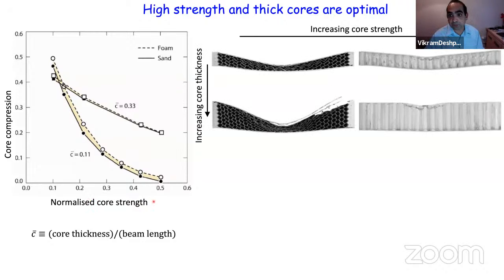strong core helping. Okay, so to give it visually, to explain what has really happened, is this story here: as you increase the core strength, you hardly compress the core, as you can see. This is a weak core, it's compressed a lot and it's lost all its bending strength, while this core strength remains very large. If the core strength is large, you retain this separation of face sheets and you basically retain the bending strength and it performs well. And if you increase the core thickness, the same thing happens: in the highest strength case, you've retained this separation, and that's giving you the good effect.